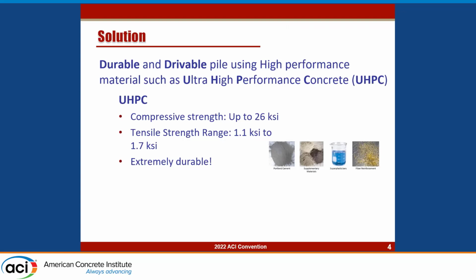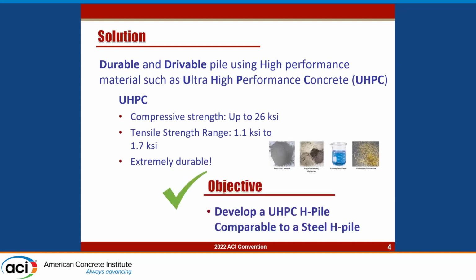Because of these components, we can get compressive strengths up to 26 KSI. We can get sustained post-cracking tensile strengths ranging from 1.1 KSI to 1.7 KSI if we use that 2% by volume of steel fibers. And it is very durable. So as such, UHPC is pretty well suited to our task, which is to develop a UHPC H pile that is comparable to a steel H pile.